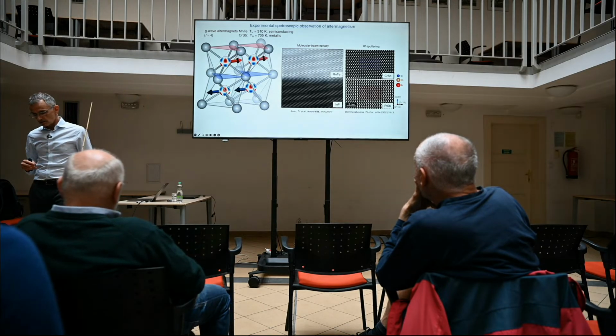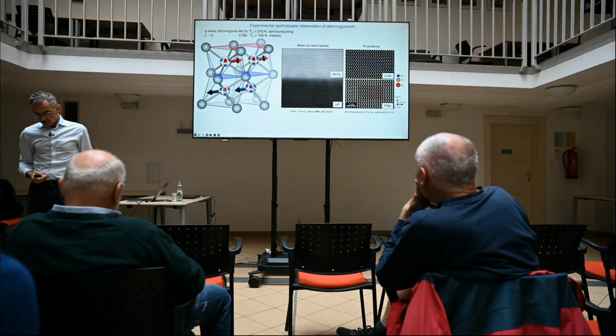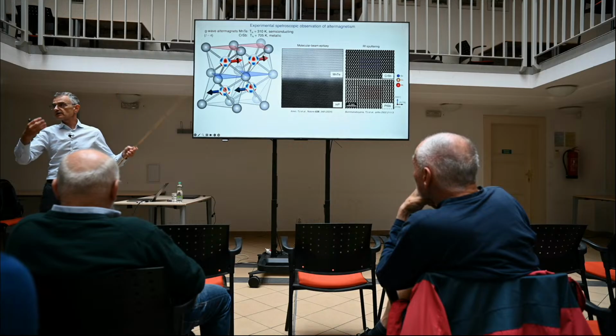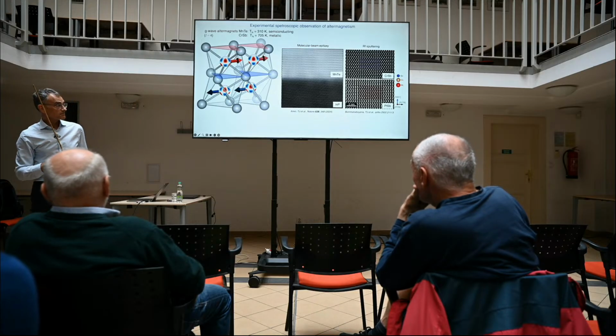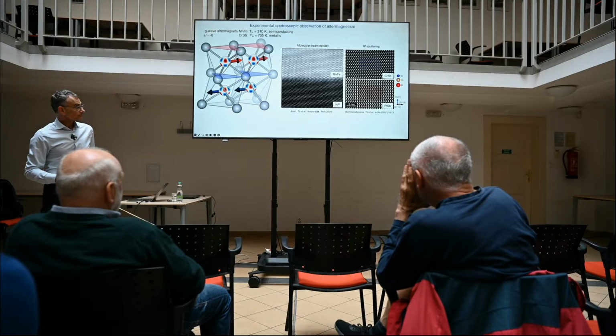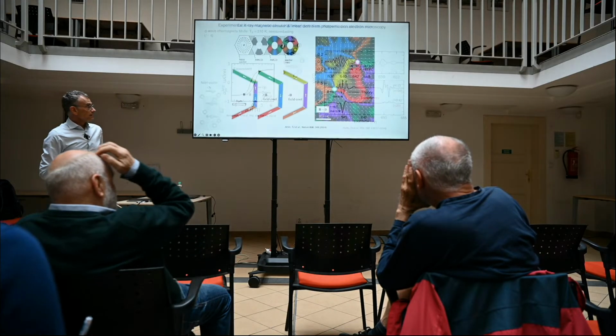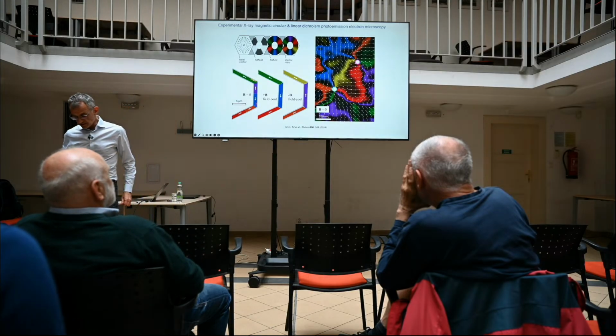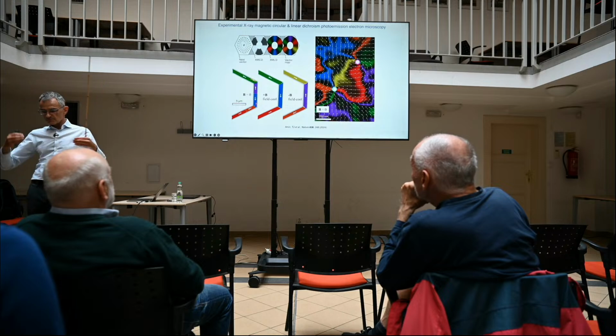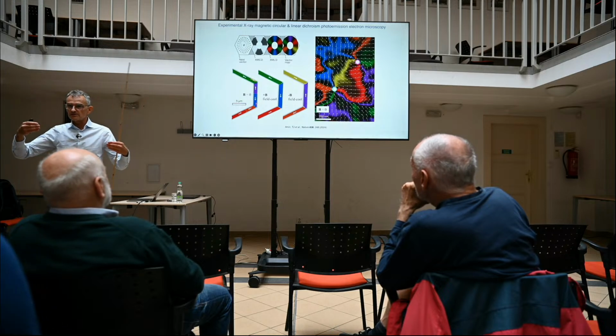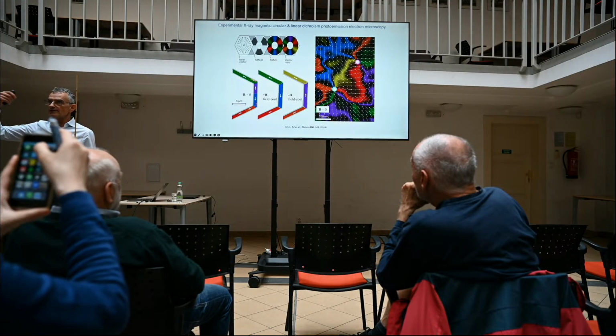Then we go to the synchrotron, and we look at the spectra by doing angle-resolved photoemission spectroscopy. One thing that turns out to be extremely important: if you want to see the spin polarization, and we also do spin-polarized ARPES, so it's not only energy and momentum resolved but also spin resolved spectra that we can get from these detectors, you have to be able to prepare a single magnetic domain on your several tens of microns sample, because this is the size of the X-ray beam that they use.